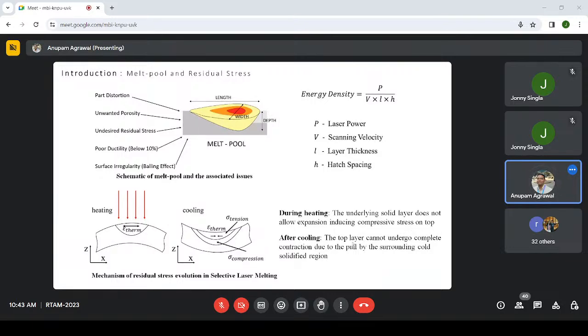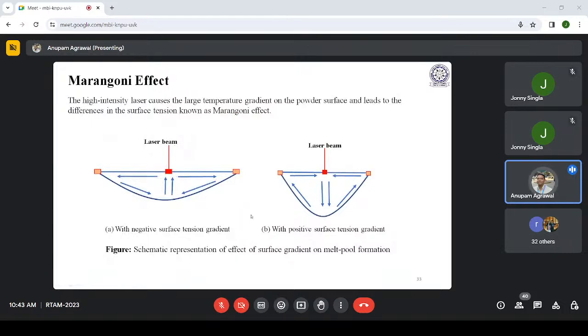After cooling, the top layer cannot undergo complete contraction due to the pull by the surrounding cold solidified region. So tensile stresses and compressive stresses, both types of stresses are there, which build up the residual stress in the powder layer, and which leads to part distortion later on if the residual stresses are not relieved. Okay, the other effect that I was talking about was the Marangoni effect.